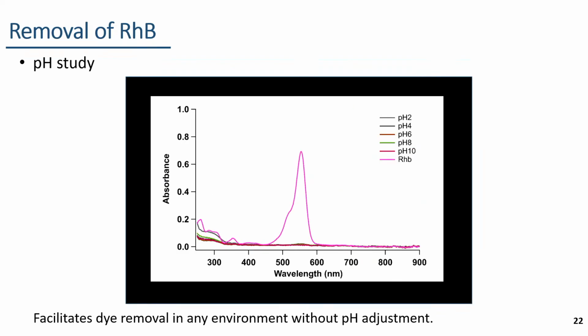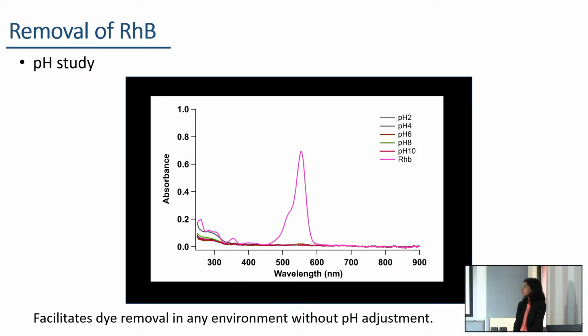Then the effect of pH on the removal of rhodamine B dye was measured over a wide range of pH values. Here we can see that the adsorption of rhodamine B onto this GEO-based composite shows an independent nature with the variation of pH of the environment. That means there is no need for any pH adjustment during the dye adsorption process. So by looking at these variations, we can see it is independent of the pH of the environment.